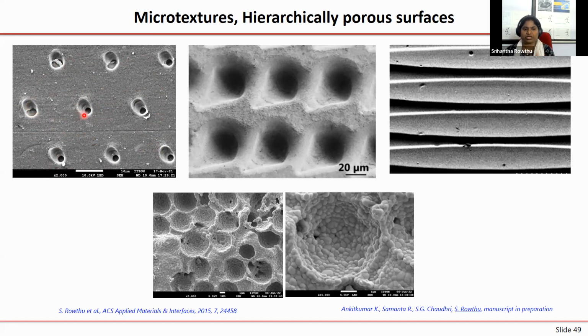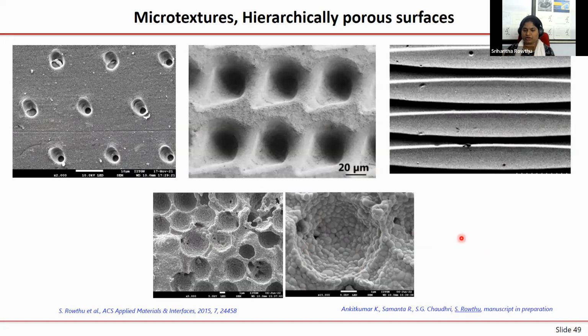Not only this sort of dimples, but also this tear shape, like a triangular sort of shape. Even such topographies I have made, and then these sort of ridges we can make. In principle, if you zoom in on any region, you will see that there are also mesopores as well as these ridges, so the sample is not fully dense. Recently, in the SRB project, my postdoc was looking at another templating methodology, and they are able to make these micro cavities, and if you sinter them carefully, you can also have some small mesopores. Right now the samples are ready, and we are about to test the tribological properties of these patterned surfaces.